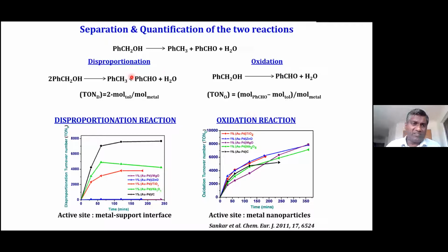So based on these simple calculations, we can calculate the turnover number for the disproportionation reaction and the turnover number for the oxidation reaction, although this happens in the same pot. So we cannot separate these two reactions physically, since they happen simultaneously in the same pot, but based on the stoichiometry, we can separate these two reactions more or less quantitatively.